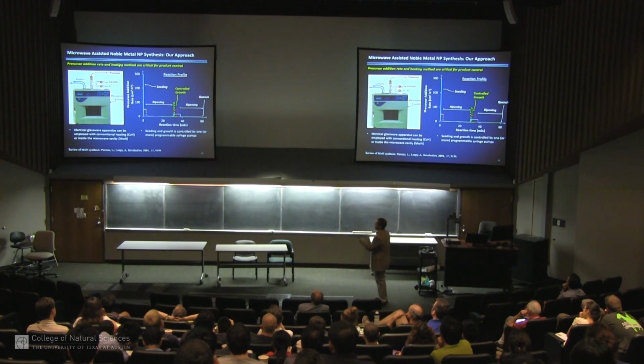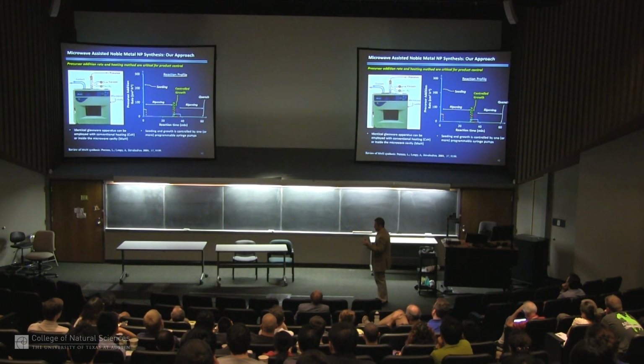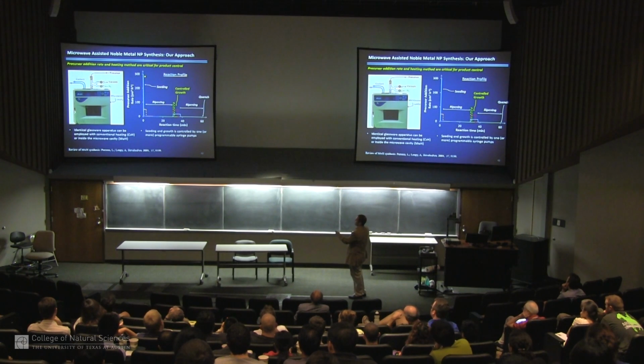And we also control the addition of our molecular precursor using a syringe pump. And we did a couple of years of exhaustive work on the conditions, and now this is just robotic, reproducible, works every time. So for example, we fire in a small amount of precursor to begin a seeding process, then we may change the addition rate, which is all controlled by the syringe pump, and this allows us to kinetically control the shapes of our nanoparticles.